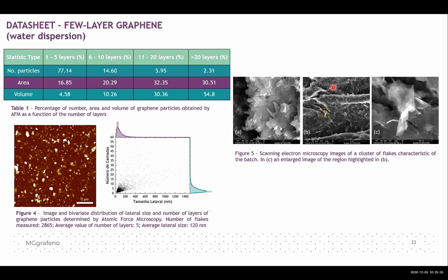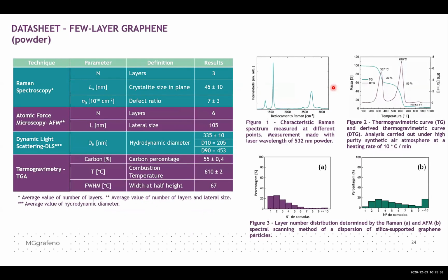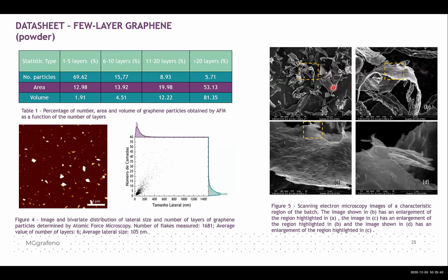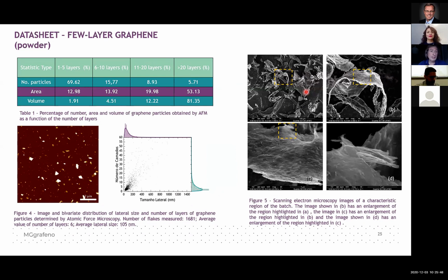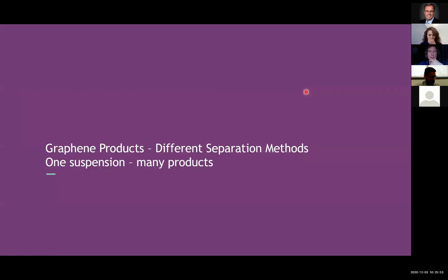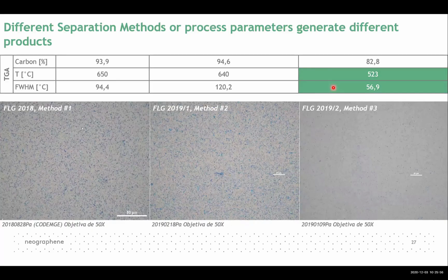So we can do this for the water dispersion. We can do this for all the material produced, for the few layer graphene. We can do this for the dried material. So we always can redisperse the dried material and do the AFM, and everything is put into the characterization sheet. And also, as I said, if you take a suspension and you make different separation processes, you can get different materials, where you can see here, right, in this case.